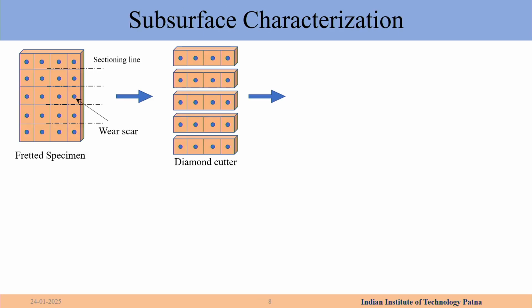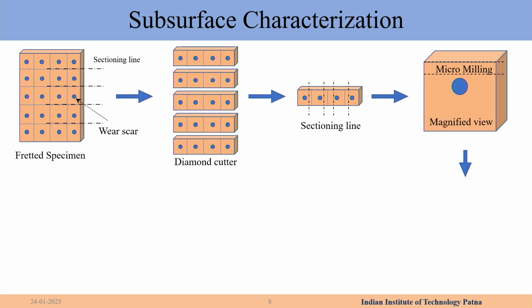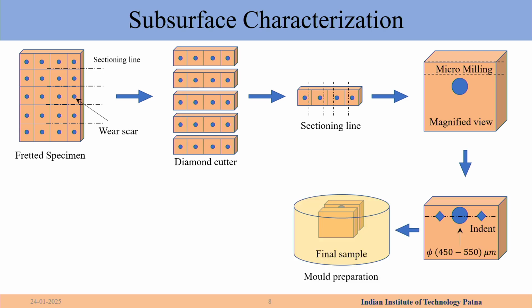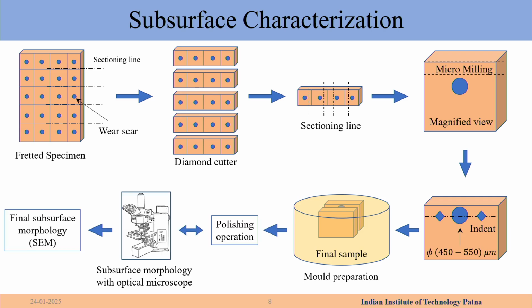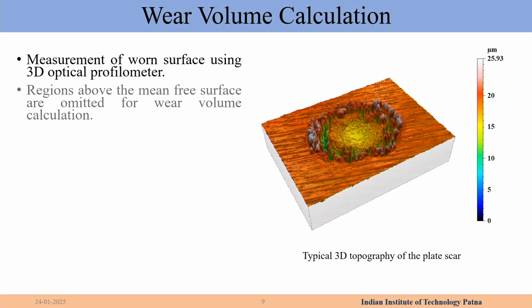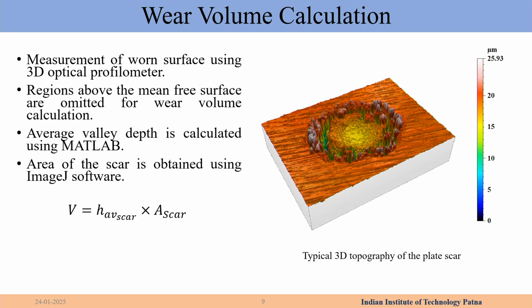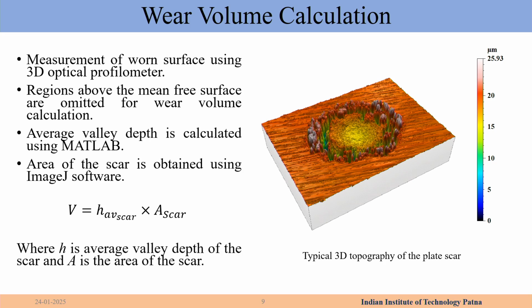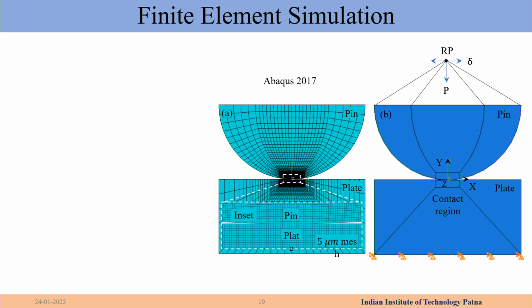So the subsurface characterization, there are steps to this actually. We have to take each of these samples, section them out, do diamond cutting, micro milling, then indenting, surface, and then SEM. Okay. So wear volume is estimated by finding out the depth and the area, and this is done very commonly. We put it in MATLAB. Optical profiler, we have an optical profilometer in situ in this tribometer. Volume is average height times the area of the scar.